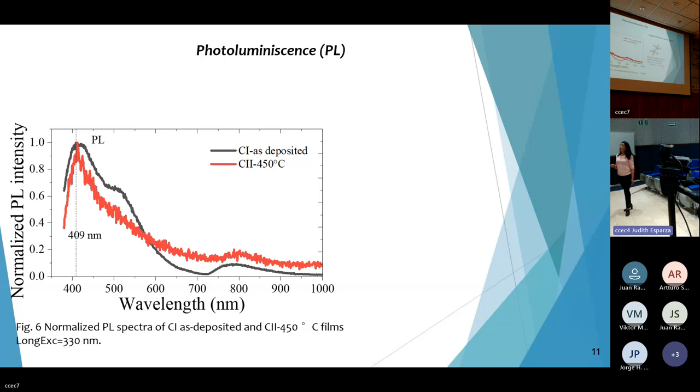The other important band is at 450, related to neutral oxygen vacancy, related to oxygen deficient centers. There is probably another contribution related to non-bridging oxygen hole centers.